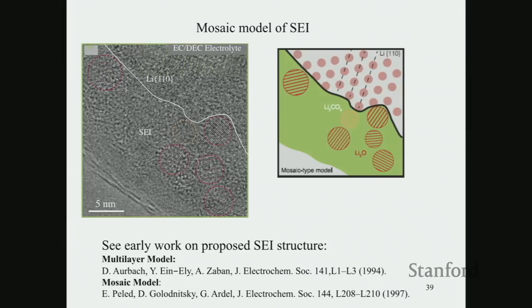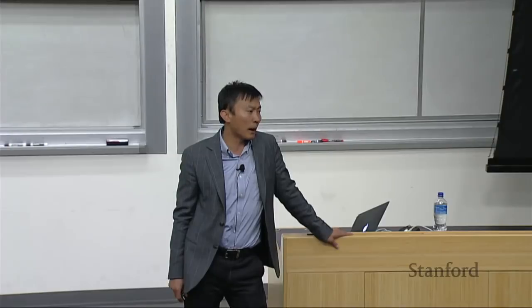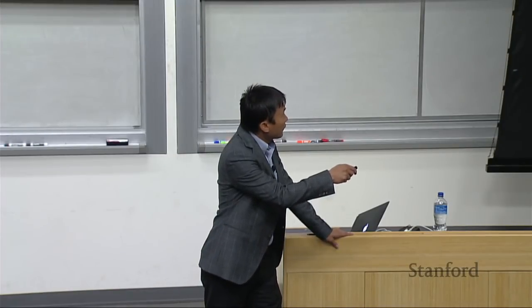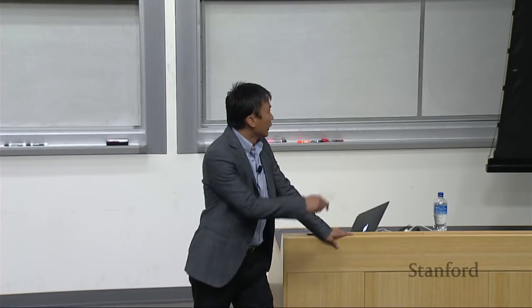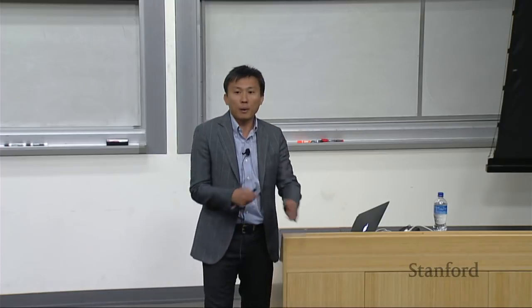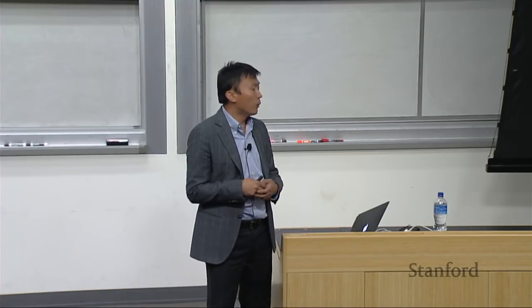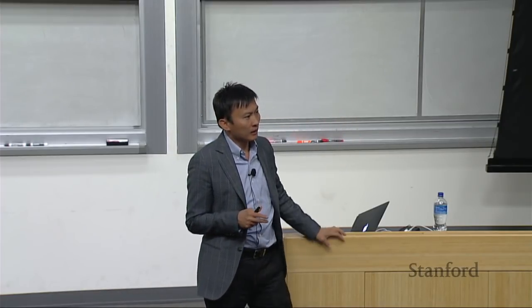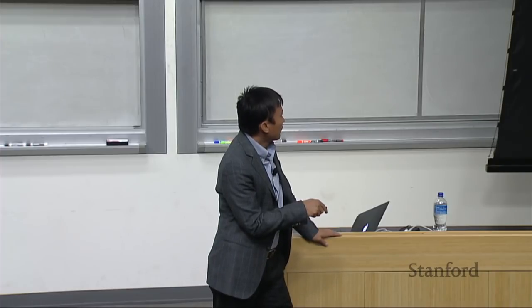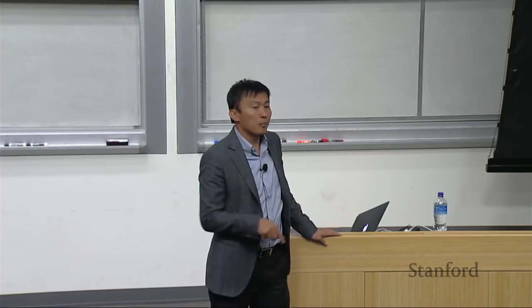There's also a long outstanding issue in the battery research field. That could determine the battery safety to a very large degree. That can also determine the battery life, how many cycles you have, how many years your battery can run. That is actually the interface, the solid electrolyte interface. There were 2 models proposed in the past couple of decades about what the structure is at the surface, the interfacial layer of these materials. There's a multi-layer model, and there's a mosaic model.